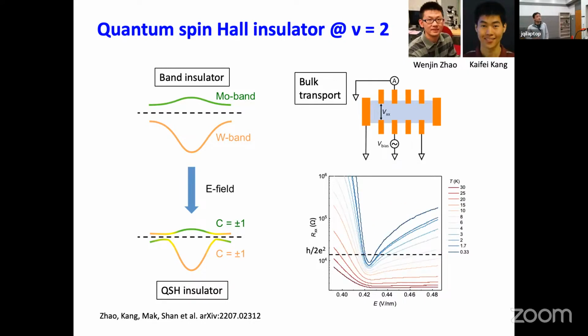To further convince you that that is the case, we measure on the same device, but slightly change our measurement configuration. Instead of a standard 4-point measurement, we try to force the current to go through the bulk of the material. We bias AC in one of the electrodes here and collect the current from the other side, but we ground these additional 2 electrodes. So we make sure that the current that we measure really goes through the bulk of the material without going through the edge. It's like an effective Corbino type of measurement.